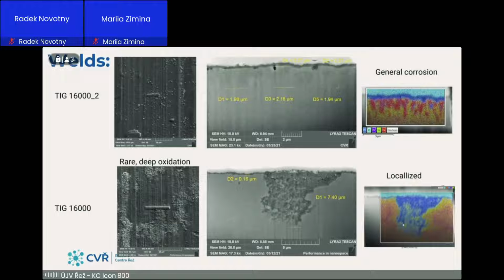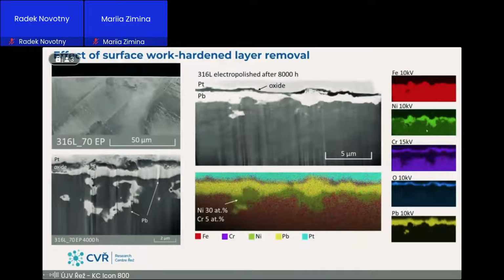That looks like that. You can see here that there is nickel concentrated around this. This chromium is here, and these green spots are nickel-rich alloys. That probably opens the path for a localized nickel dissolution, because nickel is highly soluble in the liquid metal. We tried removing this fine grain layer from machining by electropolishing, and what we get here is immediate attack in between the grains by lead. After 8,000 hours, you can see in the nickel phase the dissolution happens. So it's maybe the mechanism of how in the long term this large-scale dissolution attack develops. But because the solubility of nickel is one order of magnitude lower in lead than in lead-bismuth, we do not have as severe a problem as I demonstrated on the first slide there.